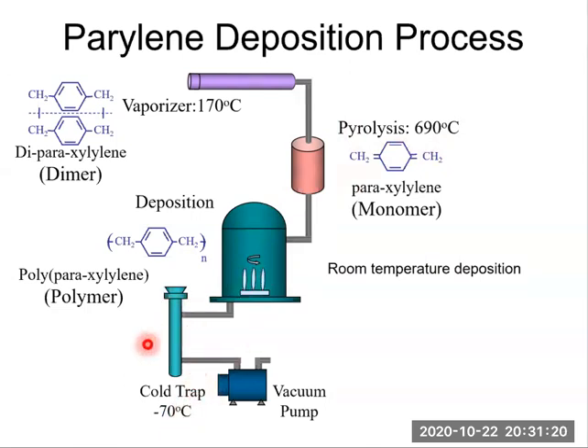And we use the cold trap to remove the unreacted monomers. A vacuum pump is used to create a vacuum inside this deposition chamber. So this is a typical parylene deposition process.